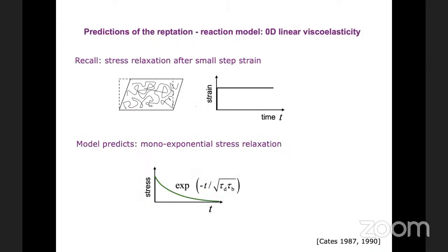It's actually rather rare in complex fluids to have such a simple mono-exponential stress relaxation. Typically, for example, in unbreakable polymers, you would have a much slower, often a power law decay of the stress because you have things happening on lots of different scales as different bits of the molecule manage to escape their tube, for example. Similarly, in a compressed emulsion where you have tightly packed soft particles compressed together, you would typically see power law relaxation as well, to do with a glassy-like or jam-like disorder in the system. But nonetheless, these worm-like micellar surfactants are a very nice example where you see a mono-exponential relaxation. So this is the first kind of rheological experiment that I introduced earlier on.